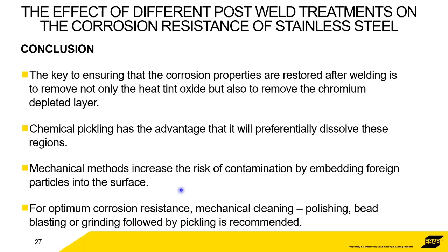But for optimum corrosion resistance, the absolute best that you could possibly do is to do a mechanical clean and polish, and then followed by pickling. So if you do both, then you're absolutely covered, and you're returning the material back to its original form, its original state.